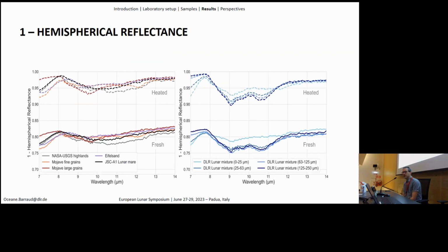So this is a hemispherical reflectance that we took. You can see on the left panel, this is heated and fresh. You can already see that there is a difference. So when you heat up the samples, there is a trend in making the sample darker. So the 1 minus reflectance is higher because, of course, the sample has lower hemispherical reflectance. We show 1 minus reflectance because it is almost similar to emissivity. Since the main product is emissivity, you will see something closer to that.